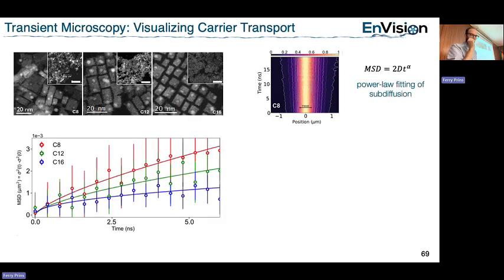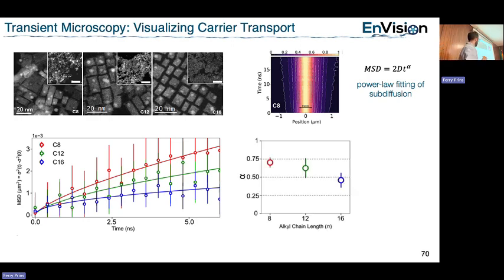Now we get the same kind of plot, but it's inverted. C8, which are the biggest particles, is the one that diffuses the best, whereas the small particles diffuse worse. And if I do my same power law fit of the subdiffusion, we see that alpha is getting lower, meaning it's slowing down faster for the particles that at first sight look better, but apparently have a lot of energetic disorder.